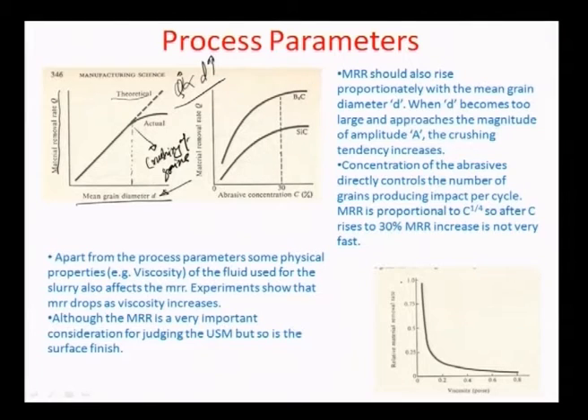And the moment this crushing phenomenon happens, as you know, the MRR goes down. So the actual value of MRR for a higher diameter grain, greater than let us say a critical diameter D1 here, would not be following the theoretical trend, it would actually start coming down. And so it is true with concentration. So for example, if you keep on loading the grains in the slurry at higher and higher concentration for two different materials, it has been proposed here, let us say for boron carbide with a different grain hardness and silicon carbide with a relatively lower grain hardness, you can see that with the increase in the abrasive concentration the MRR kind of plateaus.